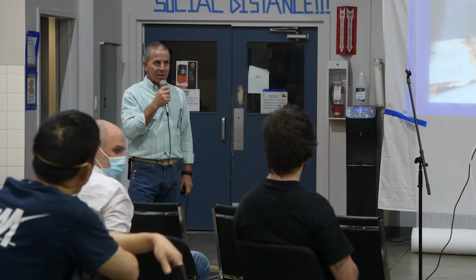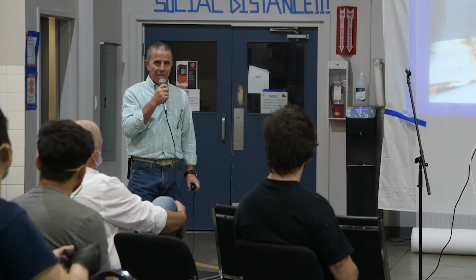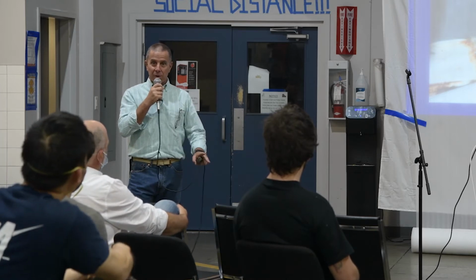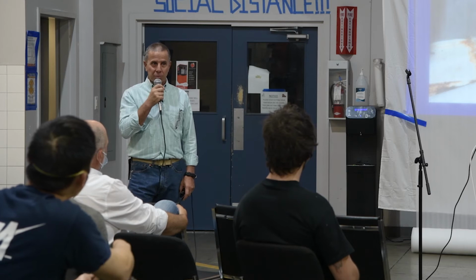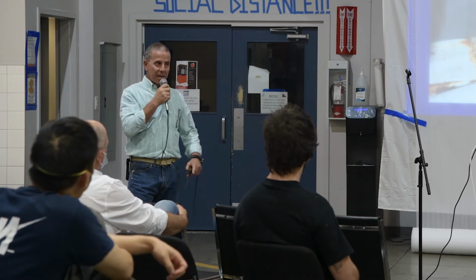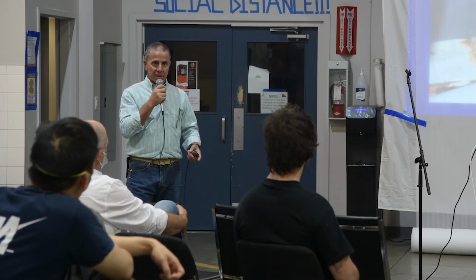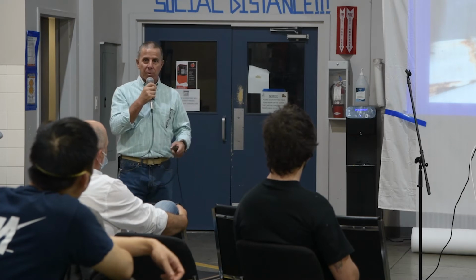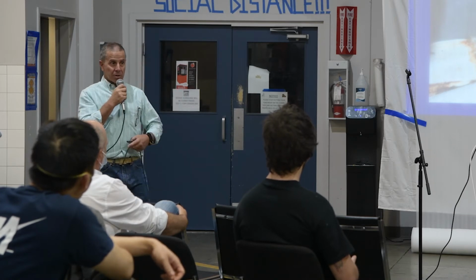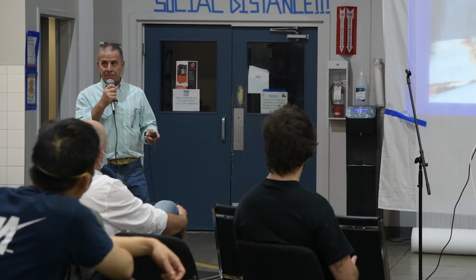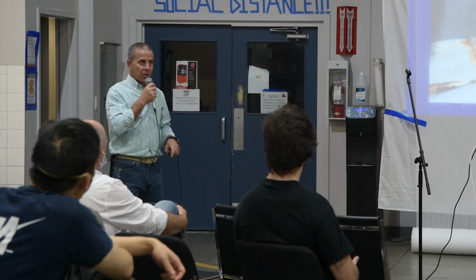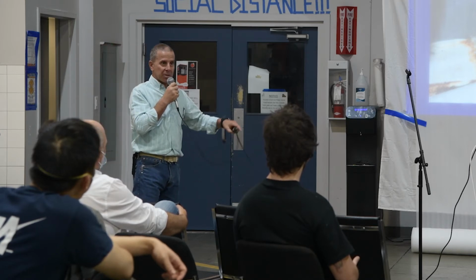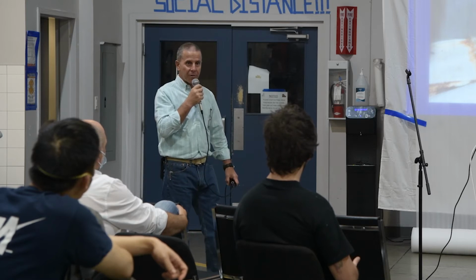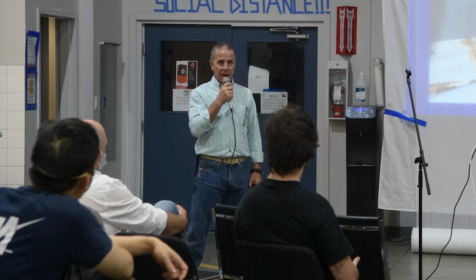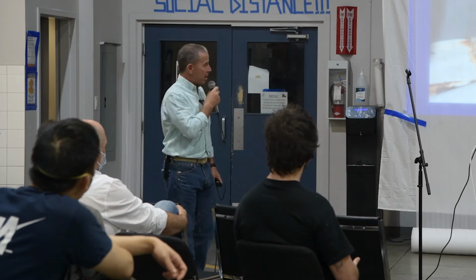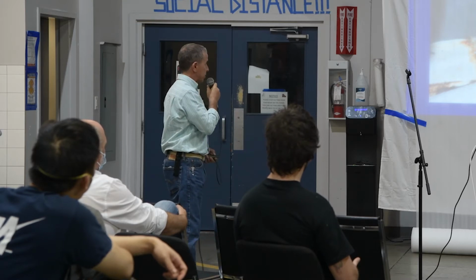So pretty much anything that you let touch aluminum, any other metal, except for two other metals which are more corrosion prone, and those are zinc and magnesium, anything else that comes into contact with aluminum and is in the presence of an electrolyte, which can be just atmospheric moisture, you will end up with corrosion. Some of it is worse than others. As I said, copper alloys are especially unfriendly to aluminum in that kind of scenario, like copper wire, but almost any other metal will cause this to occur.